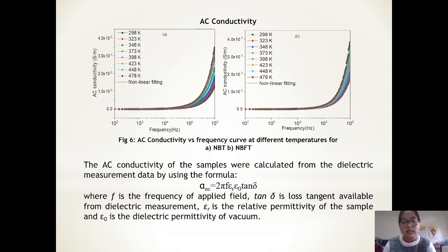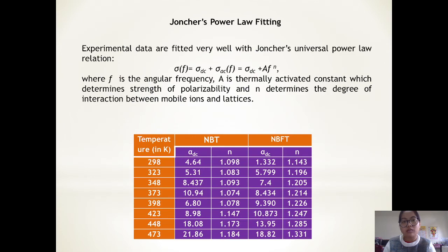The AC conductivity data were very well fitted with Jonscher's power law, and the value of DC conductivity and n, which determines the degree of interaction between the mobile ions and lattices, were calculated. From the table, it can be seen that the DC conductivity increased with increase in temperature. This may be due to the thermal activation of conduction mechanism.